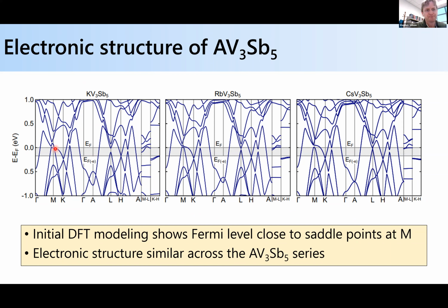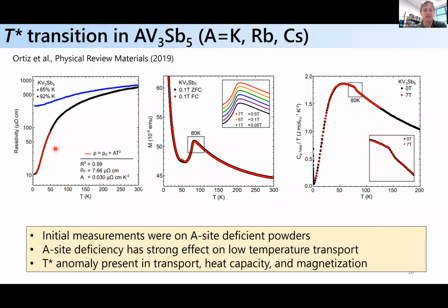And if you were to look at the systems, this is experimental data collected on powders, as I've shown you here, for the potassium system, potassium, vanadium, 3 antimony 5. If you look at the transport, you can see it's a metal, but this is transport done on potassium deficient materials, as extracted from powders. For instance, the black line is missing 8% of the potassium sites. The blue line is missing about 15%. So you can see that the low temperature transport is very sensitive to the degree of occupancy on this A site.